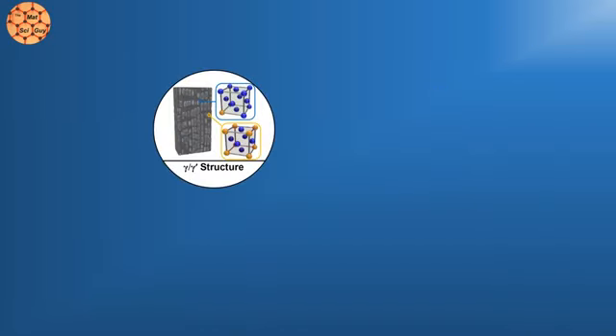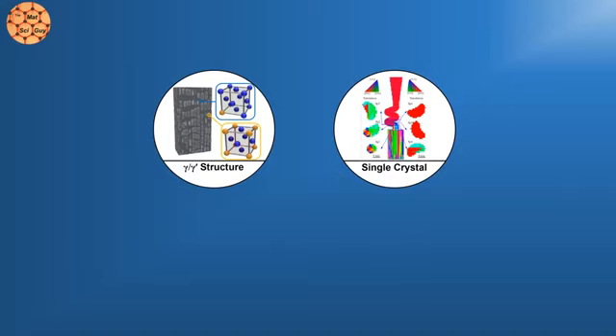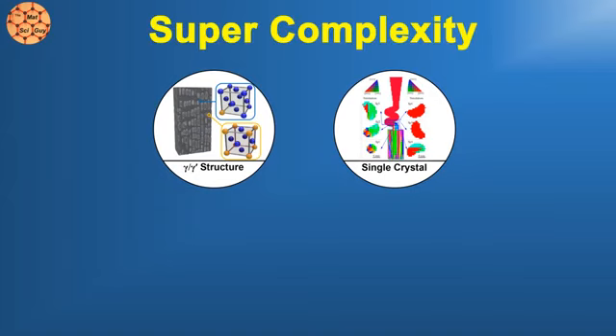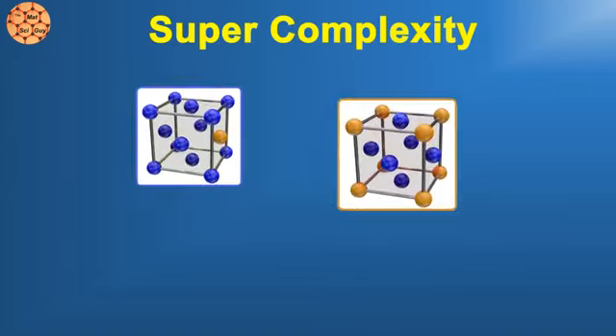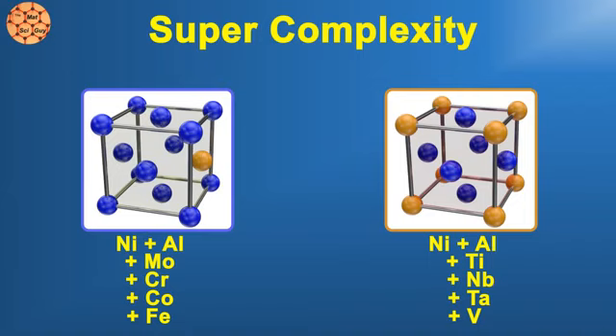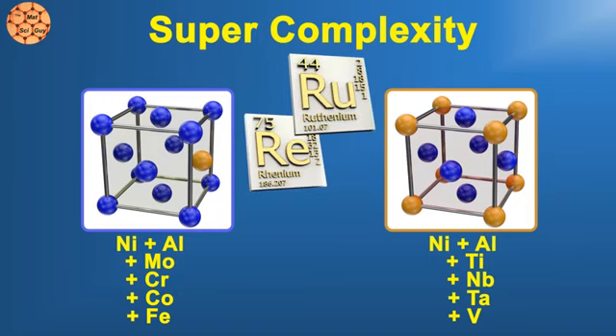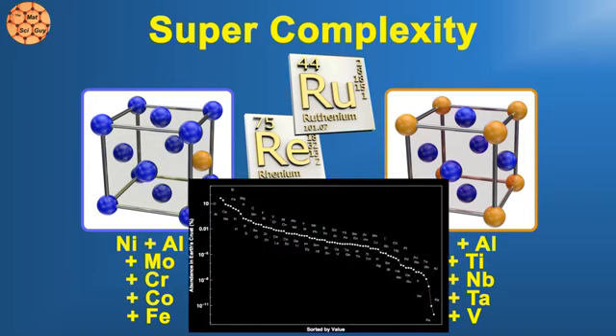The unique phase structure and single crystal nature are two of the most interesting and unique features of superalloys, but the truth is that we've only scratched the surface of superalloy theory and design. Other alloying elements like molybdenum, chromium, cobalt, and iron are often added to strengthen the gamma phase, while titanium, niobium, tantalum, and vanadium can further strengthen gamma prime. The latest generation of superalloys even have metals like rhenium and ruthenium added for increased high-temperature strength and stability. These are two precious metals rarer than gold. It's an unbelievably complex system, and to this day millions of dollars are put into research and development to further refine and optimize these alloys.